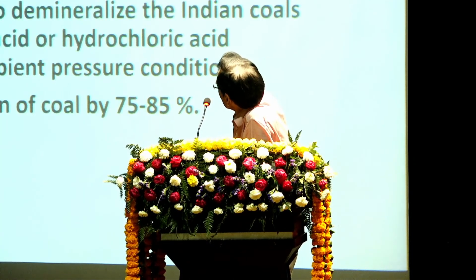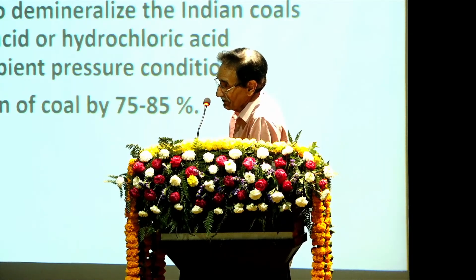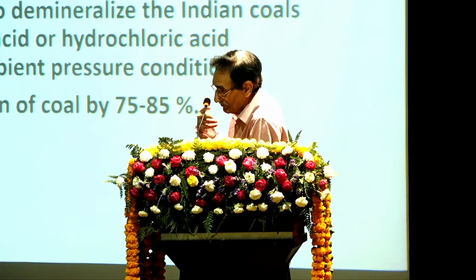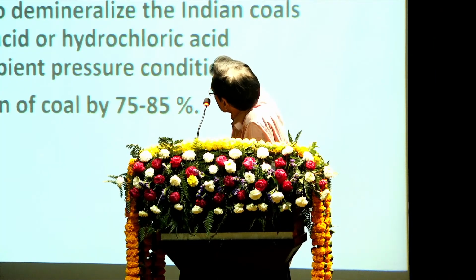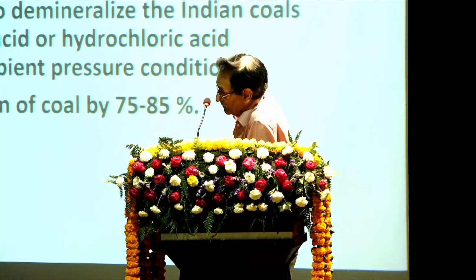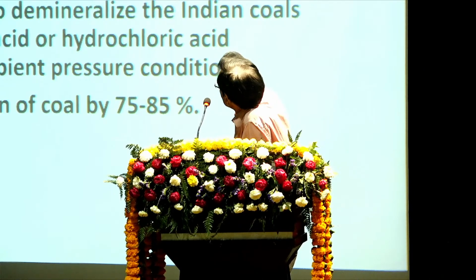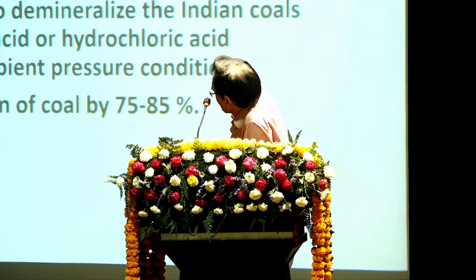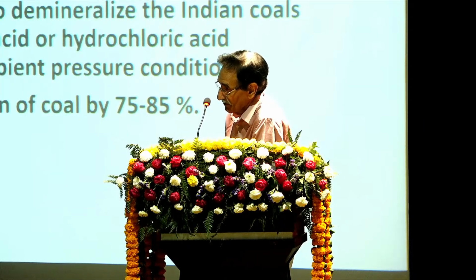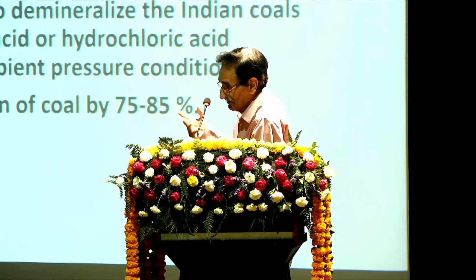Next slide. We thought of using that super clean coal for getting graphene and carbon nanotubes. So we collaborated with NPL, and we used the DC-arc discharge technique to convert this super clean coal into graphene and carbon nanotubes. In parallel studies, we were getting 80% removal of ash by using alkali followed by acid, NaOH followed by sulfuric acid leaching of coal. Those coals were also used for getting carbon nanotubes and graphene. Next.